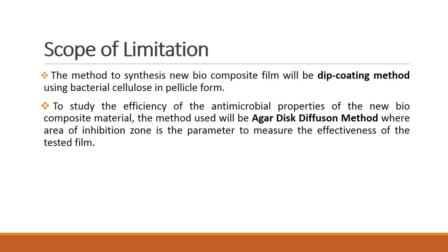For the scope of limitation, for my research, the method that I use to synthesize the new biocomposite is the dip coating method, which means the bacterial cellulose in pellicle form is dip coated into the antimicrobial agent. Besides, to study the efficiency of the antimicrobial properties, the method used will be the agar-disc diffusion method. In this method, the area of the inhibition zone is the parameter to measure the effectiveness of the tested film.